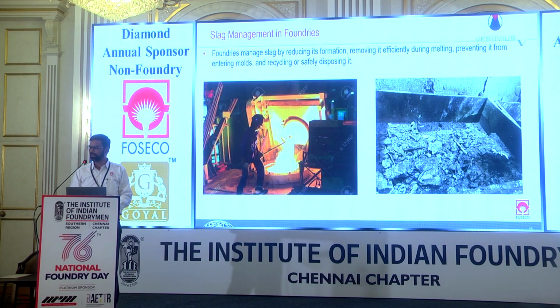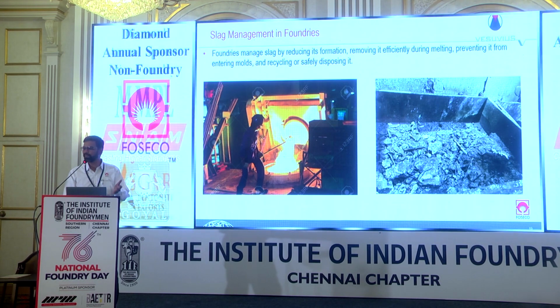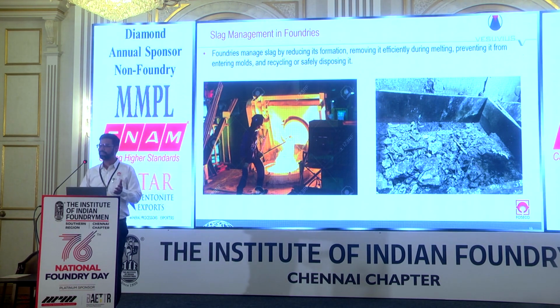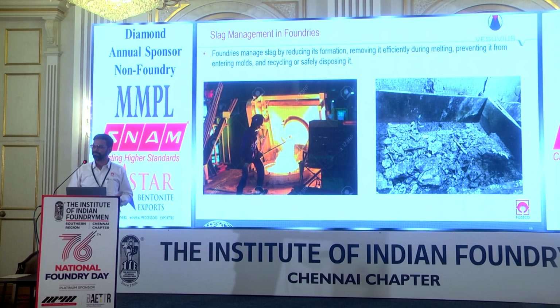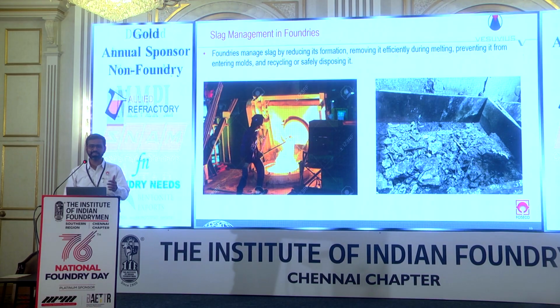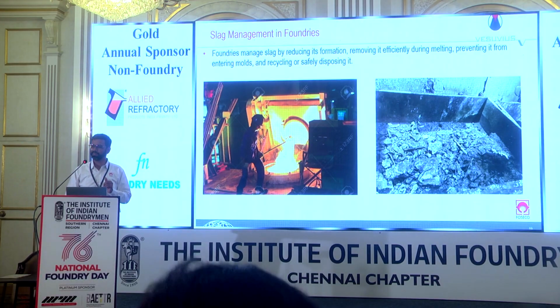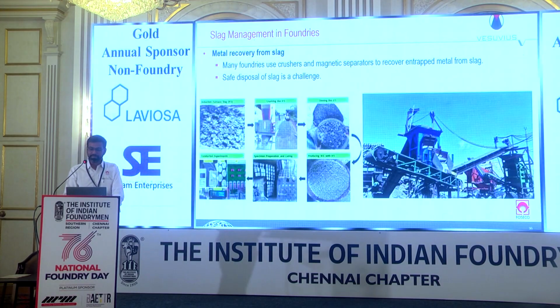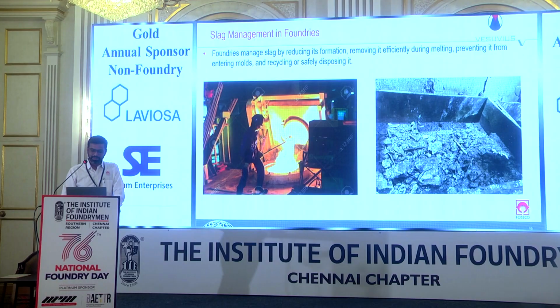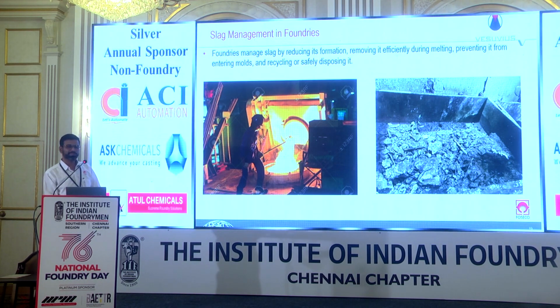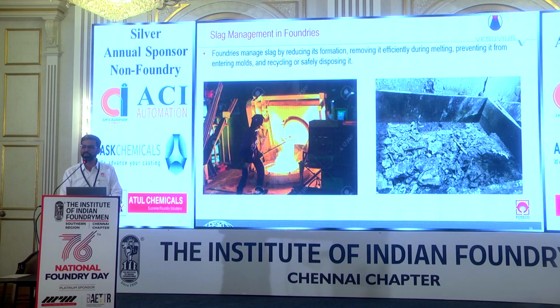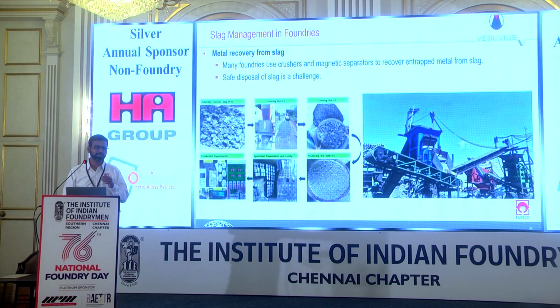It will deteriorate the casting performance. To manage slag, first foundries use clean scrap as much as possible so that slag generation itself will be lower. However, slag generation is one part. Another part is how we remove that slag before we pour the casting. For slag removal, normally these rods are used, as you can see in the picture. This is one of the popular practices, and we know that during this slag removal, along with slag, metal is also going away.